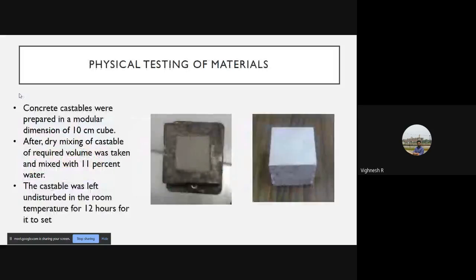The second one was a physical test done for the refractory castable. When you think about concrete, we have water, cement, coarse aggregate, and fine aggregate. We mix it up and pour water into it. When we got the castable from the seller, it was a dry mix, so you just needed to add water, and you get this really good mix that you see in the first photograph, in the mold. 11% of water was added to it, and we kept it inside the mold.